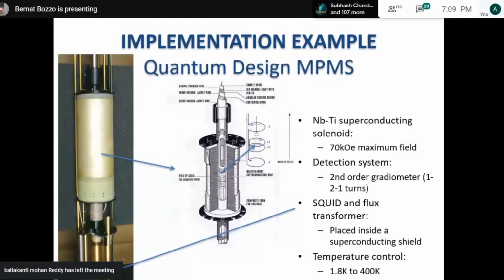This is the image of the real magnetometer. This is the solenoid which we use for the magnetic field. In the center of the system, we have some sample space. Surrounding the sample space, we have the second order gradiometer, which is made entirely of superconducting wiring. The sample is placed at the end of the sample rod, so we can move it up and down. This will cause a magnetic flux change in the solenoid, and will give us the signal that we can treat to determine the magnetic moment of the sample.